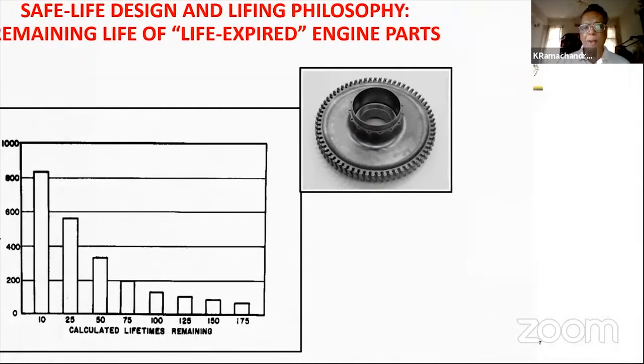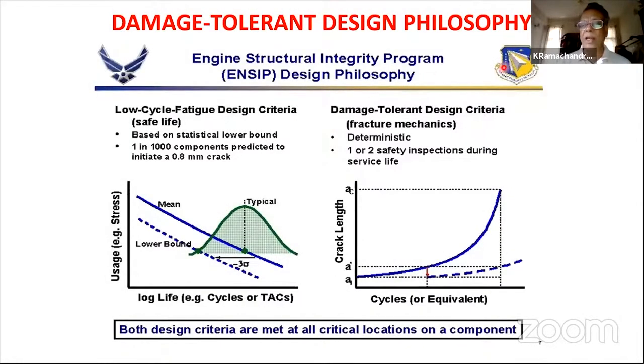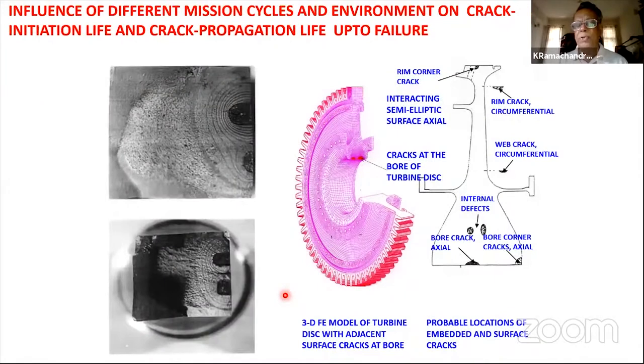And therefore, today we are talking about what is called damage tolerant design, which is fracture mechanics based. We should understand how the cracks propagate, even if a crack has developed, what is the rate at which and the direction in which the cracks grow, which is very deterministic. Whereas the safe life method of looking at the life of the disc based on low cycle fatigue design criteria is more of a statistical lower bound. And therefore, we tend to gain a lot of cost advantage, and the life cycle cost of the system goes down tremendously. But the catch is, we should understand the materials, we should understand the components, and we should understand the behavior of the component with reference to existing or already developed cracks or defects in the system.